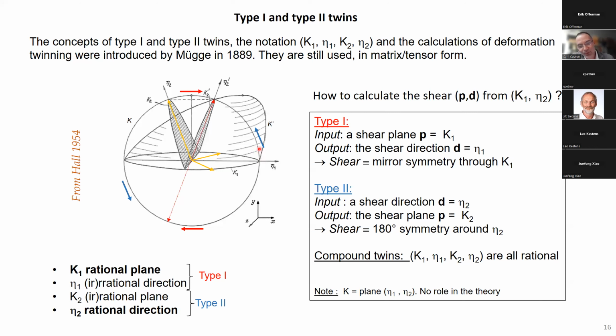Okay, to create a new plane K1 prime that is not represented in this figure. And by doing that, I can calculate the image of K1 prime. I can calculate the intersection of the 2, which gives this direction here. And these 2 directions, eta 2 and this direction, are left invariant by the twinning operation. It means that the K2 plane is invariant.